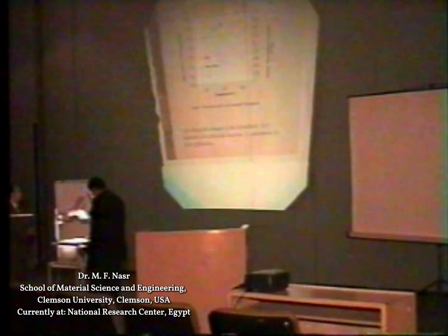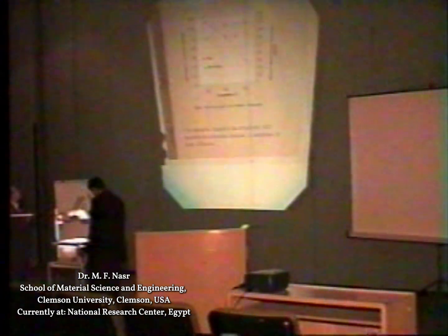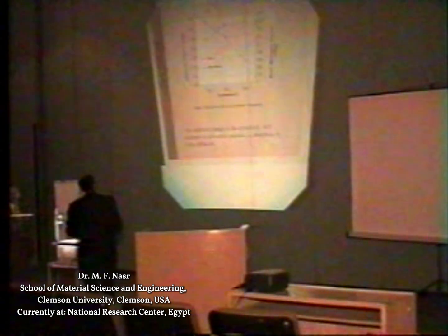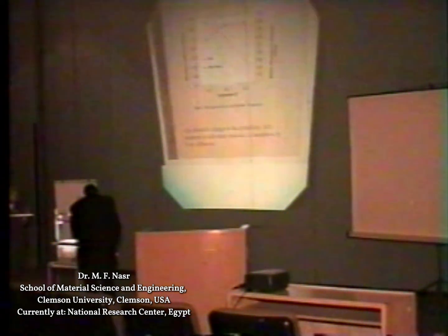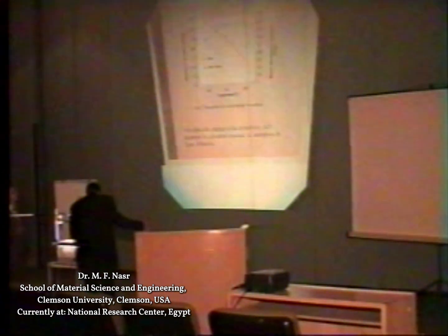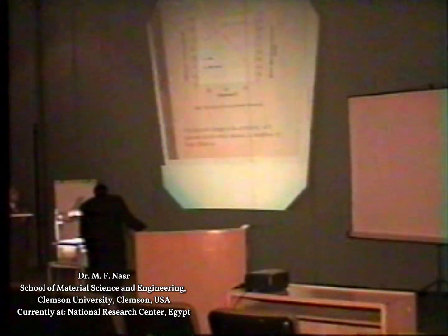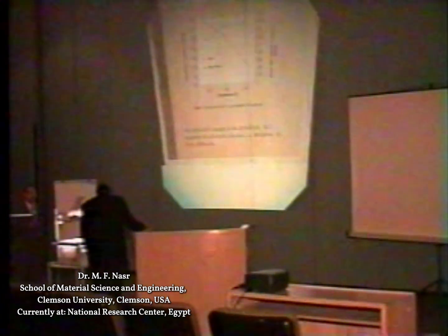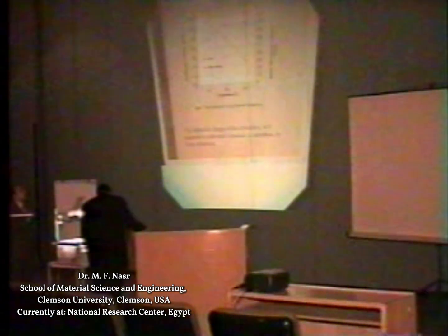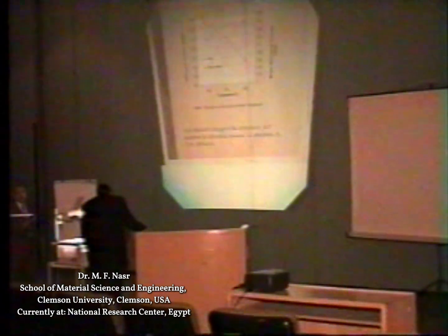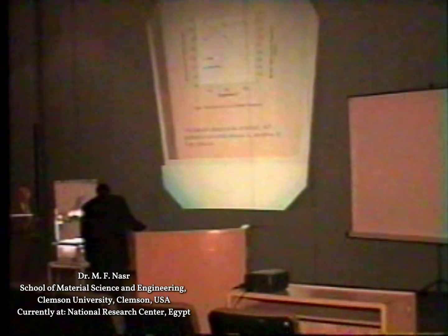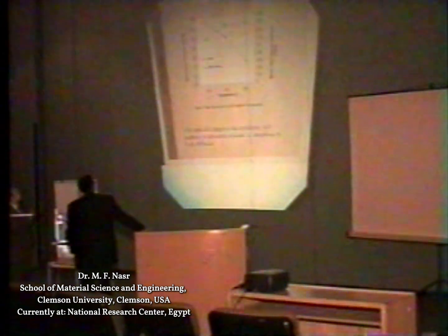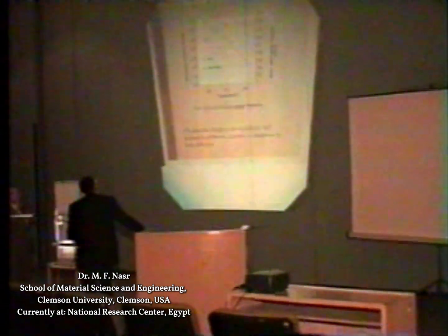By measuring the pore volume, we have, like I said, two types of pores: the micropores, which are less than 2 nanometers, and the meso and macropores, which are larger than 2 nanometers. Of course, we like to have a big pore volume because it's much easier to fill these pores or to play with them, instead of the smaller pores, which are less than 2 nanometers.